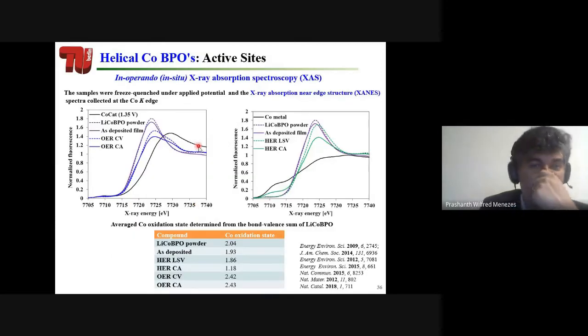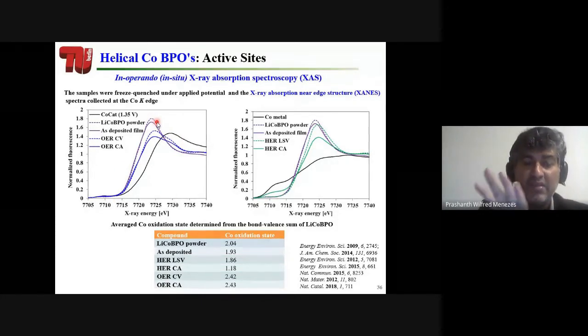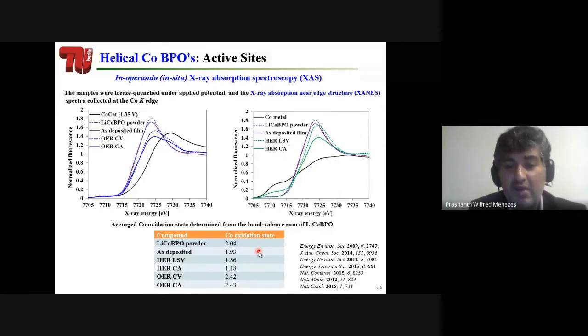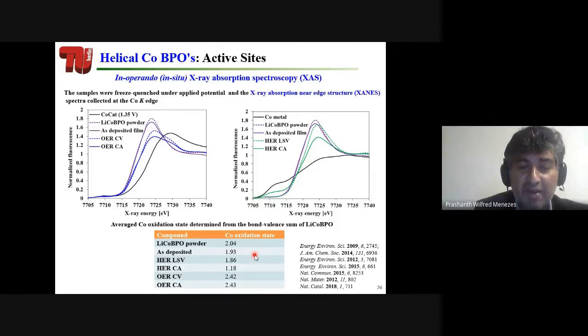So, okay, this is how it looks like. This is the X-ray absorption near edge structure. What you can get here is the oxidation state. That's it. So this is what we measured for oxygen evolution reaction, and this is what we measured under hydrogen evolution reaction. And what we see here is that our material had an oxidation state of +2 in the powder state. In the deposited state, we had a slightly lower oxidation state, which is still closer to 2. And then during hydrogen evolution reaction, our catalyst was completely reduced. Similarly, in the oxygen evolution reaction, our catalyst is completely oxidized.